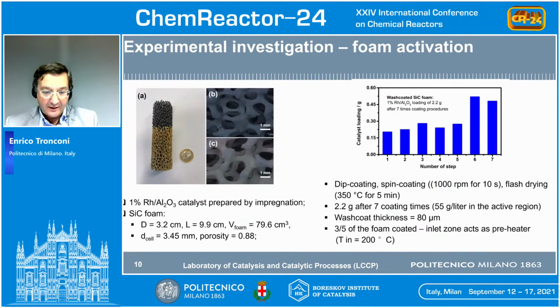To make the silicon carbide foam catalytically active, we wash coat it with an active homemade rhodium on alumina catalyst formulation. Partially, we wash coat only about 3/5 of the whole catalyst sample. The initial part is used for preheating purposes. The overall catalyst loading is in the order of 2.2 grams, so 55 grams per liter for our foam sample. And this was obtained by 7 replicated processes of dip coating and spin coating according to a procedure that we have developed in our labs. As shown by the SEM images on the left, we were able to achieve a reasonably good homogeneous coverage of the catalytic foam without any evidence of pore clogging phenomena.